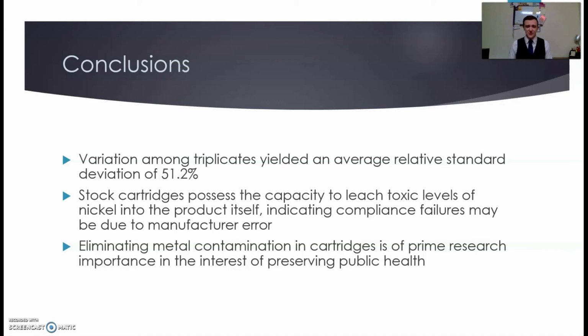This is also an end user, a consumer issue, the people that are actually using these cartridges. Due to the high variability in how nickel is leached into these products over time, cartridges which have already passed compliance testing and therefore been labeled as safe can very easily later be found with concentrations of nickel which exceed the action limit due to metal leaching. Therefore, this could be a huge public health concern due to the fact that cartridges which have been labeled as safe by the state of Michigan are therefore getting into the hands of consumers with toxic levels of nickel.